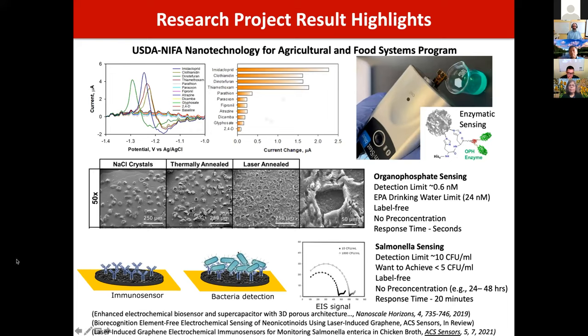Same with salmonella, using a similar type of sensor but with an antibody, we can get a detection limit of about 10 CFU per mL. Ideally we want to achieve that one CFU per mL that Sam was talking about before. But again, this is label-free, with no pre-concentration. And pre-concentration usually means incubating that bacteria for 24 to 48 hours. So this is really fast, within 20 minutes.